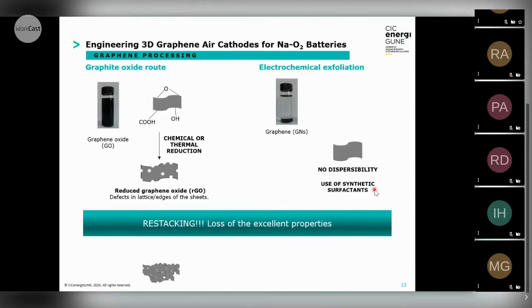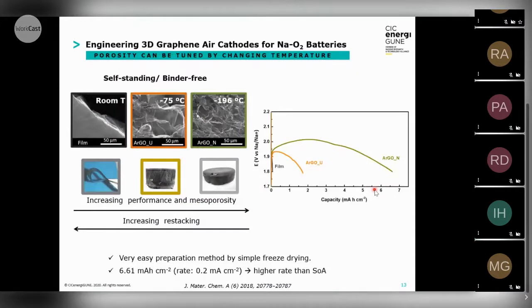And also really important when working with graphene is the restacking. These sheets tend to agglomerate, so we lose this porosity and surface area. So it's really important to engineer 3D structures in order to accommodate this discharge product in the case of sodium batteries. So the first study is looking at the Hummers method, and what we did is tune the porosity by changing the temperature. That means once we get that solution, we go to the freeze dryer and perform at different temperatures so we can get different porosities.